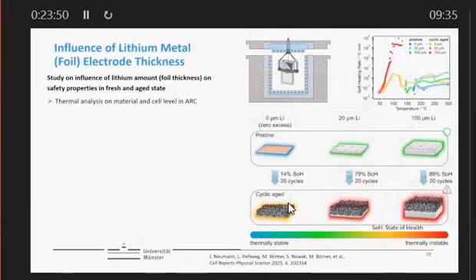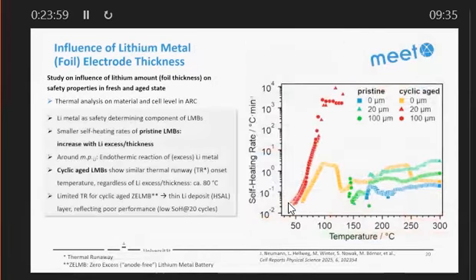So if we are looking at the influence of lithium metal electrode thickness, we get the result that you see here on the top right. And you might say, okay, this is a little bit too small to watch from the back. For this reason, I have enlarged it. And here we see the thermal analysis. And on the right-hand side, in, let's say, more dark colors, green and blue, we see the pristine cell. So no cycling. And with red, yellow, and orange, we see the cyclic aged cell.